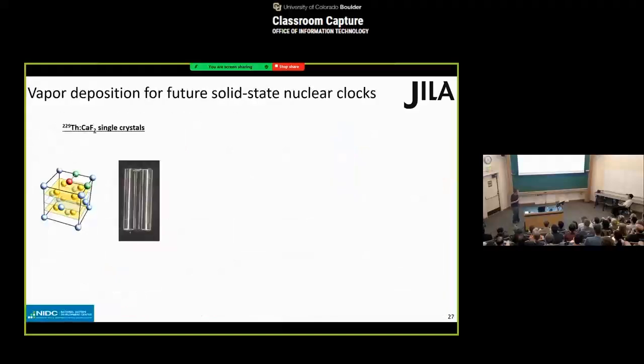OK, so now in the last couple of minutes, I want to switch gears and tell you about a different effort that we are pushing towards for practical metrology applications. So essentially, all the data I showed you were taken with these thorium-doped calcium fluoride single crystals. And they work very well. They are grown with a more or less conventional crystal growth technique, where these crystals, as grown, are on the order of centimeter size scale.